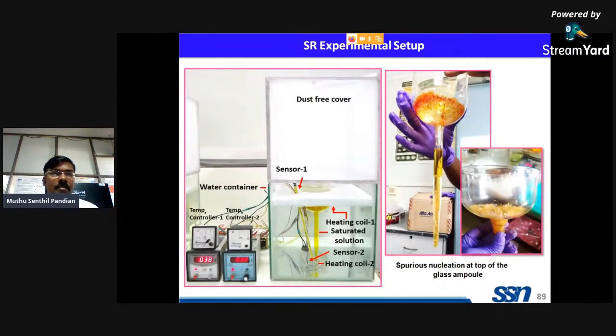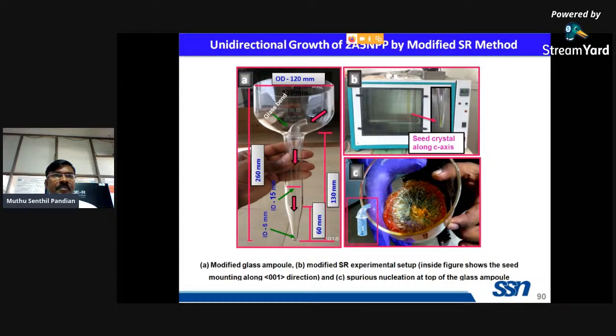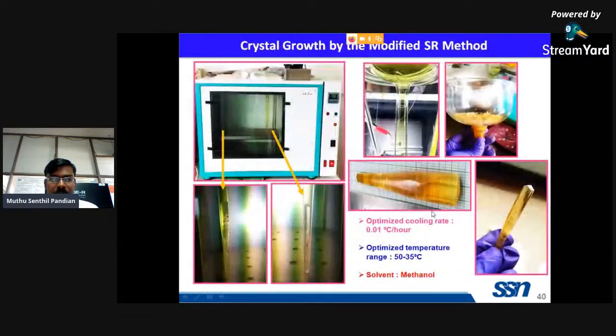We have chosen solvents like methanol, ethanol, and acetone for this SR method because the solubility of this material is very high, so spurious nucleation easily forms on the top of the SR glass ampoule. So we made a glass ampoule like this and modified the SR glass ampoule. We maintained a uniform temperature and mounted the seed at the bottom of the glass sample. If spurious nucleation forms, it stays only at the top of the glass sample, so it will not affect the grown crystals. This is the spurious nucleation formation at the top of the SR glass ampoule. Because of this small modification made in the SR glass ampoule, we have grown the 2-amino-5-nitropyridine single crystals.